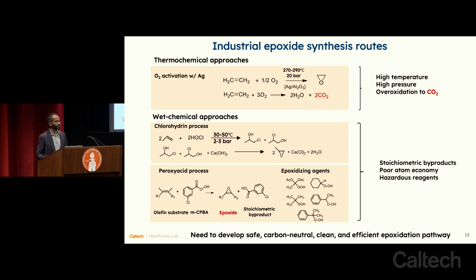This has been recognized for some time, so others have tried to develop alternative approaches. I show here, for instance, the chlorohydrin process, by which one can react an olefin with hypochlorous acid, making a chlorohydrin. This chlorohydrin can then be treated with base, calcium hydroxide, and you make the epoxide. But you also make a calcium chloride side product. And this calcium chloride side product is sufficiently a problem now because of the brine discharge that you have from those plants that permitting of the chlorohydrin process is actually decreasing now. So we're seeing fewer and fewer plants getting approved in jurisdictions that recognize the environmental challenge of having this salt discharge stream.